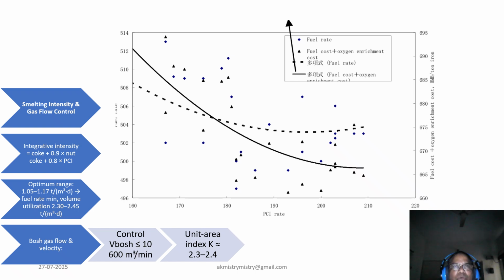This is about smelting intensity and gas flow control. We use an integrative smelting intensity metric, that is coke plus 0.9 times nut coke plus 0.8 times PCI, to target 1.05 to 1.17 ton per meter cube per day. This range minimizes fuel use and maximizes throughput. Bosh gas flow is controlled below 10,600 meter cube per minute with a unit area index around 2.3 to 2.4 for consistent blast distribution.